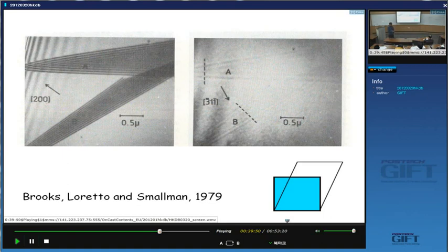So the real shape change when you get epsilon martensite is not simply a shear. So this is gamma. Okay. Then epsilon will lead to both a volume change and the shear. And the shear dimension is simply given by this vector divided by twice the spacing of the 111 planes. Okay?